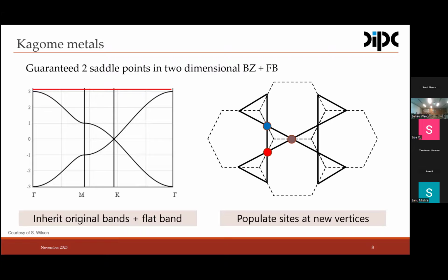But we inherited the honeycomb energy spectrum plus a flat band. The energy spectrum of this is actually derived from the s-orbital tight-binding model, which is a very simplified model. In reality, as I showed before, the electron band structure is much more complicated, but we can easily understand the Van Hove singularities and Dirac crossings starting from this tight-binding s model, which only considers hopping from the nearest neighbor. Once we put hoppings to the next nearest neighbor, the bands are no longer flat.